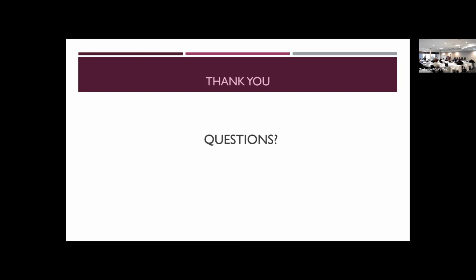A comment. In my previous life, when looking for carbonation in cement systems, we noticed that once the carbonic acid hit the cement at the interface, it densified the cement system. So maybe that's helping you improve the shear bonding, because the initial effect of carbonation is to densify the cement and reduce its permeability. The issue is once the carbonic acid is exhausted and you hit that same specimen with fresh water, that's when you dissolve the system, because calcium bicarbonate is not available, or those phases I've never seen in solid form. They're dissolved in water. So that's how your system begins to reduce, and that's how CO2 can continue dissolving your cement. That's the one comment.